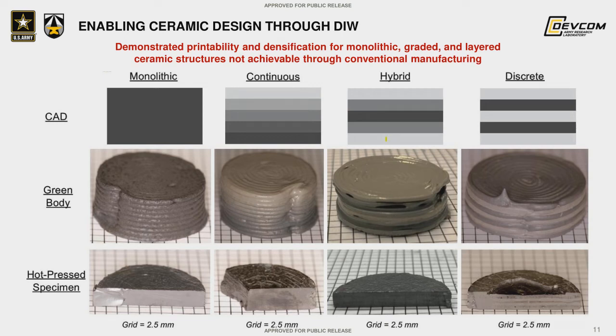So by using this system, we've demonstrated both printability and densification for a variety of different functionally graded or otherwise controlled ceramic substructures that aren't available through conventional manufacturing techniques. So we've shown our ability to create monolithic parts of a single material, continuous gradients where you have a silicon carbide material on the top going in graded steps to a fully boron carbide composition on the bottom. Hybrid steps where we go from one material to the other and back again. And then discrete elements where we have discrete layers between things like boron carbide and silicon carbide in a sort of layered structure. And then we've been using hot pressing to densify these materials to full density.